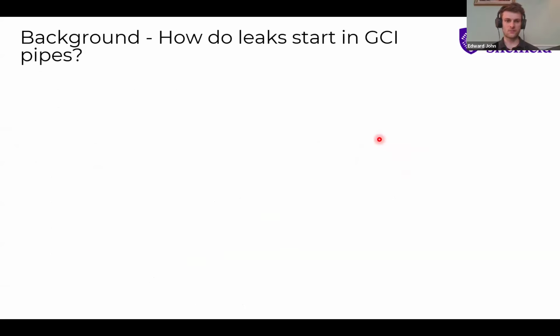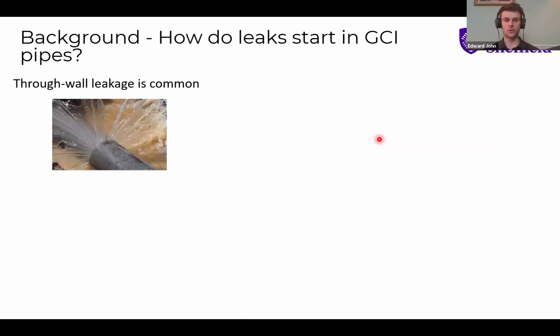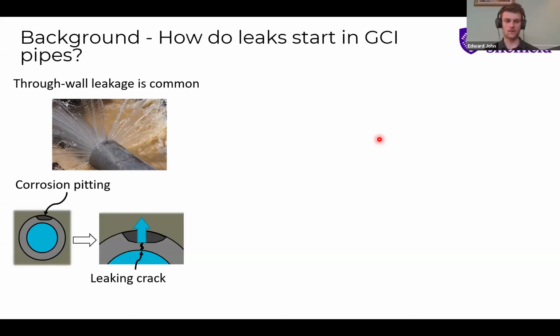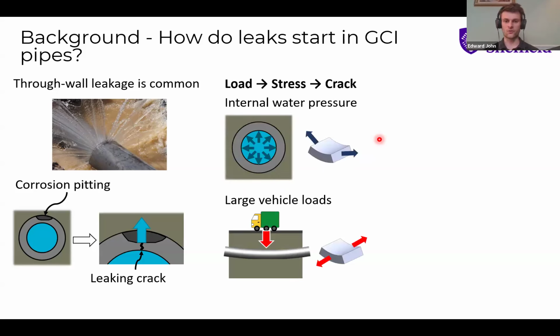So looking at cast iron pipes, what's the theoretical understanding of how these leaks start? We know that through-wall leakage is a common way that leaks form in these pipes, and that these pipes ultimately fail. The idea is that you have corrosion pitting, which effectively removes the original metal, creating weak points in the pipe and creating stress concentrations. And then under service loading, cracks can form at the base of these pits that enable water loss and leakage. These cracks are caused by the stress experienced by the pipe, and the stresses are caused by the loads applied to the pipe. So Kobus has given us a nice overview of these.